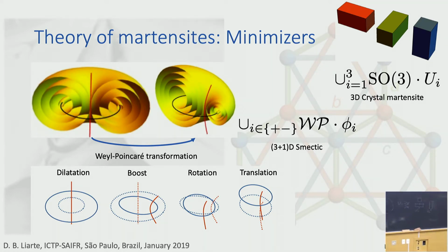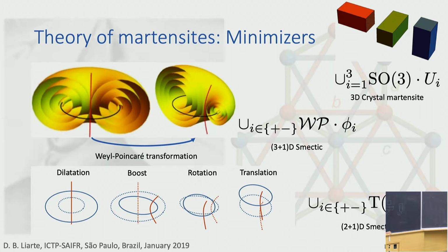You can apply a 3+1 dimensional translation. The group of symmetry that minimizes the energy for this Smectic is this Weyl-Poincaré group. It's the Poincaré group plus dilatations. And now, again, if you focus your attention on the simpler 2+1 dimensional case, what you have, for instance, is just a translation group in 2+1 dimensions. You can translate the event associated with each light cone in this XY direction and the time-like direction for this Smectic.